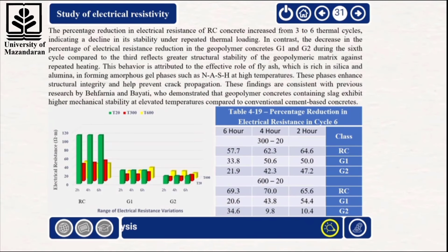Increasing the number of cycles from 3 to 6 resulted in higher resistivity loss for RC, indicating reduced stability under repeated thermal exposure. In contrast, the geopolymer concretes G1 and G2 exhibited smaller reductions in the 6th cycle compared to the 3rd, reflecting greater structural stability against repeated heating.